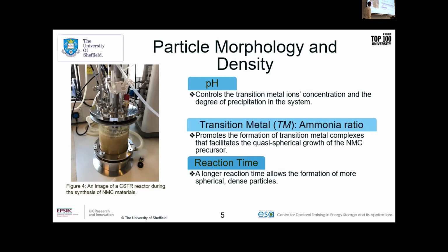So this is a stirred tank reactor that we've got in our lab. You can see how much of a nightmare it is to control. But we've got a pH probe, which controls pH. We've got different feeder tubes, making sure that the volume stays constant throughout. But yeah, it's a lot of control, and it's taken a long time for both our group and other groups to perfect and optimize this procedure, but it does pay off.